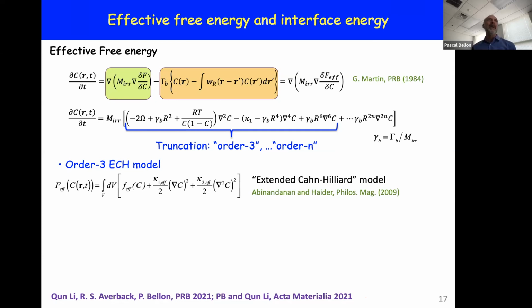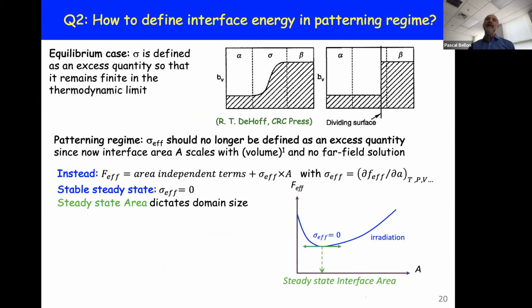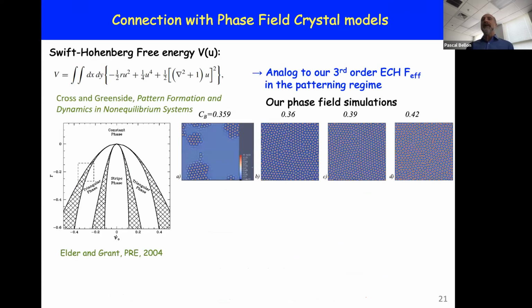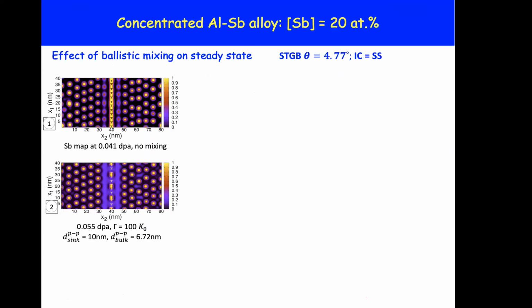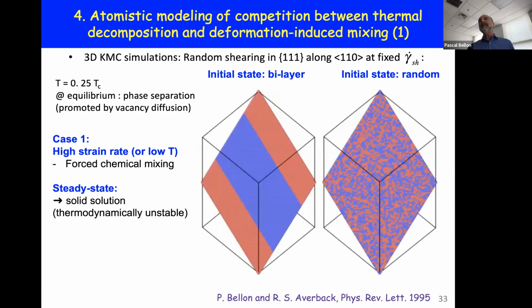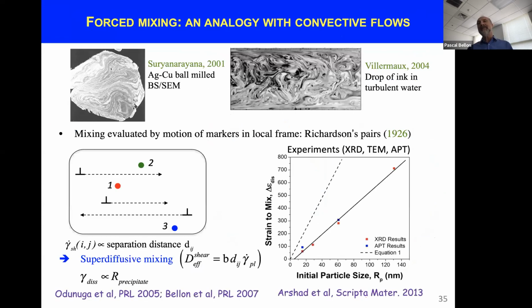The short answer is no, but every so often there are certain things that can be done. I imagine you had in mind the case of alloys under radiation, but let me use the case of alloys under severe plastic deformation, because it's one case where we have an answer that fits a little bit what you said. This super diffusive mixing, the rate at which plastic deformation randomizes a configuration, we expect it to be captured by the fact that if you start with a microstructure with precipitates, under conditions where there's no thermal diffusion, the strain to dissolve those precipitates will scale linearly with the initial diameter of those precipitates.